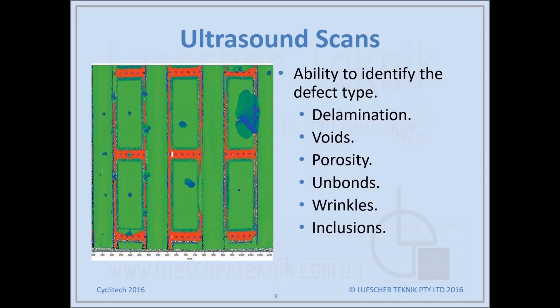So here is an example of a C scan. That's a plan view of the part, and you can see that there are different indications on the part. There's a red indication and there's a blue indication, which highlight different aspects of the scan. Those blue indications are typical of a delamination or something like that.